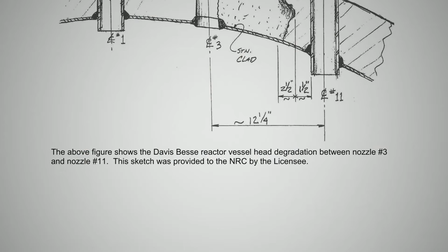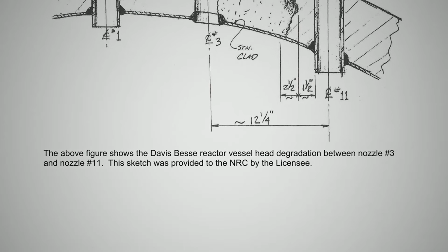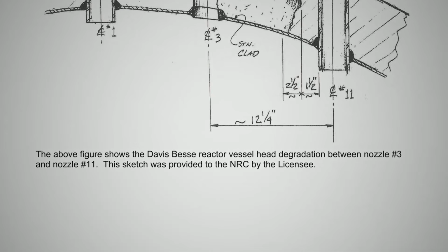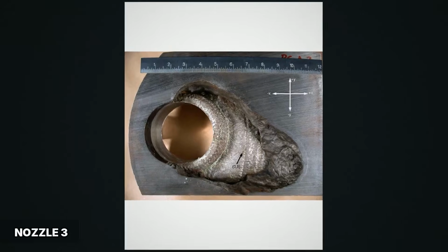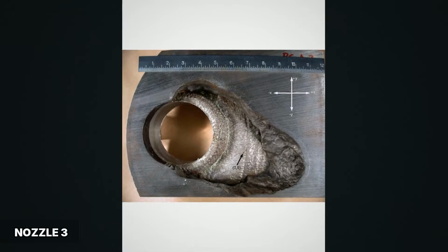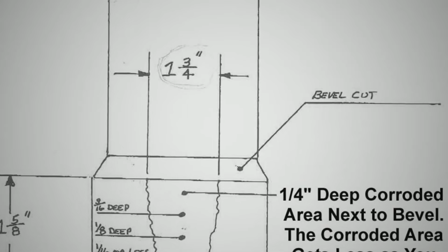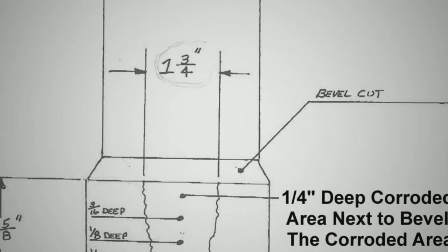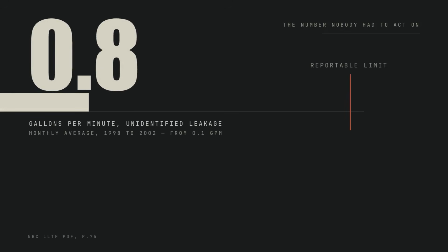Now the physics, because you need to understand why a leak this small could remove that much steel and still leave the plant running normally. Start with the crack. A nozzle made of alloy 600 develops a crack from primary water stress corrosion cracking. At Davis-Besse, multiple head penetration nozzles were found cracked. Nozzle number 3 is the one that matters. The cavity opened up right next to it. Through that crack comes reactor coolant. Not a jet. Not a spray you would see on a gauge. A weep. The leak rate was small enough that it never tripped a limit, never forced a shutdown, never showed up as a number anybody had to act on.